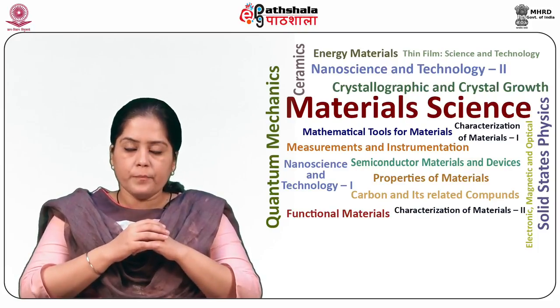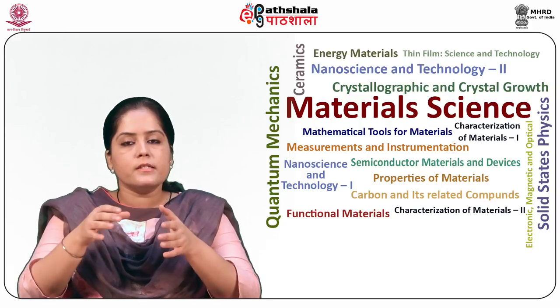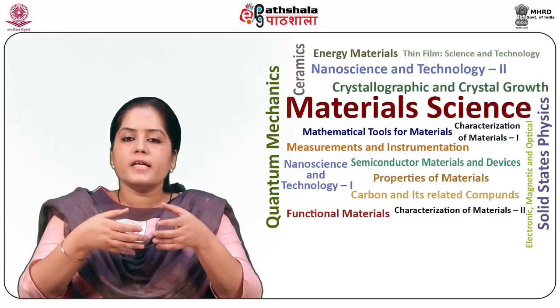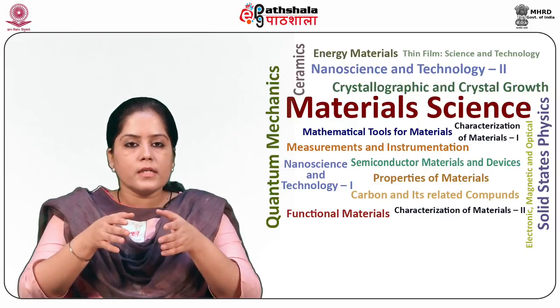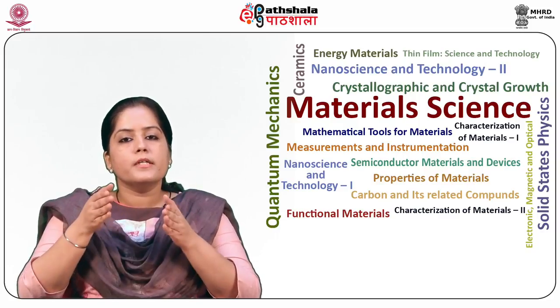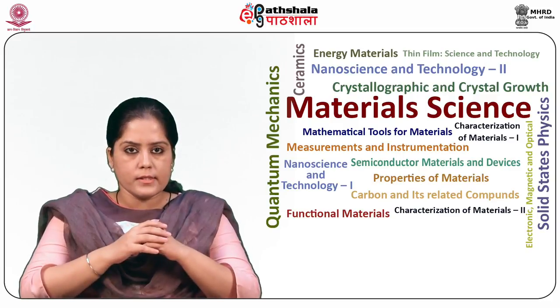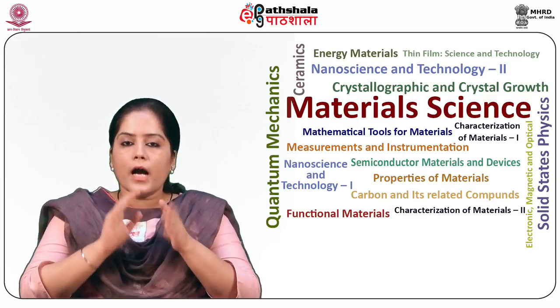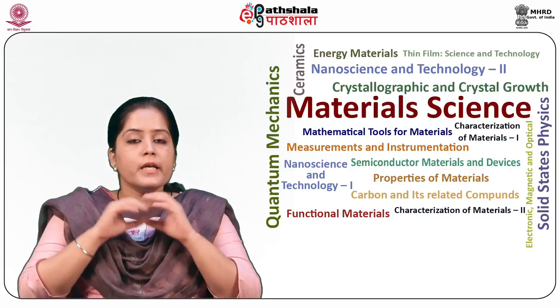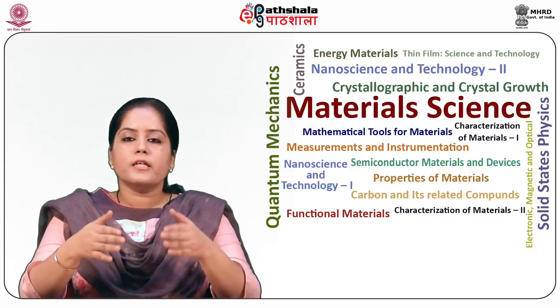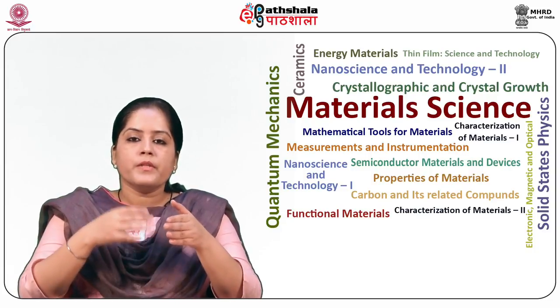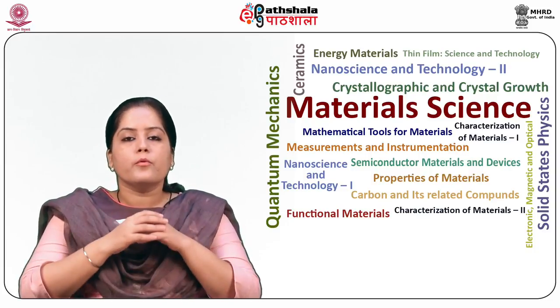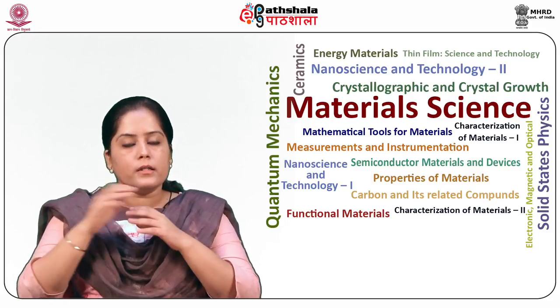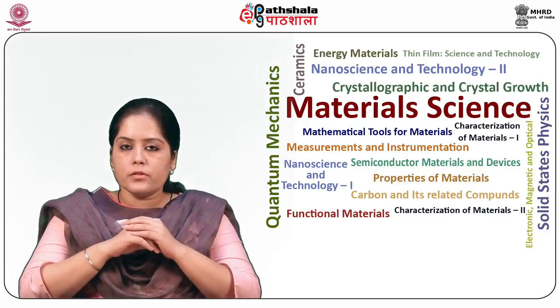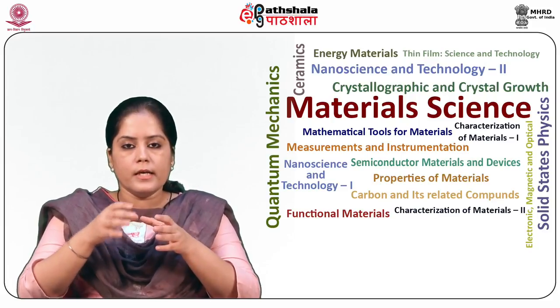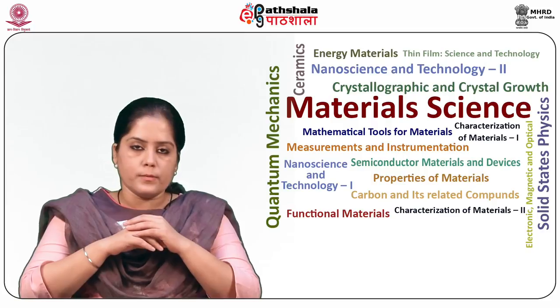Self-biasing of the target. The target automatically tends to bias itself more negatively than the anode as a consequence of the difference in the mobility of ions and electrons. The reason is that high mobility of electrons enables a larger electron flow through the anode, while the less mobile ions provide a lower current to the cathode. Due to this asymmetry, a negative bias is created through the plasma.